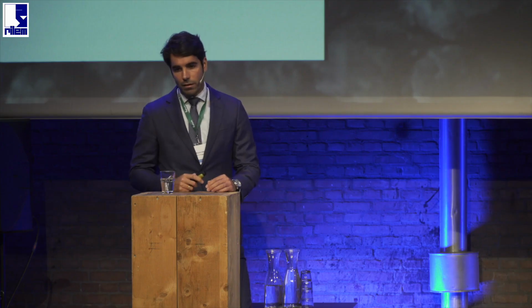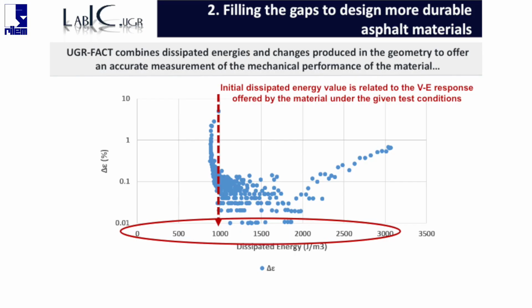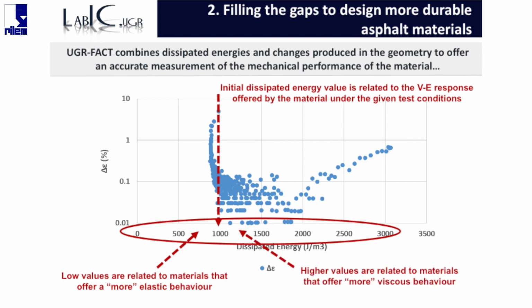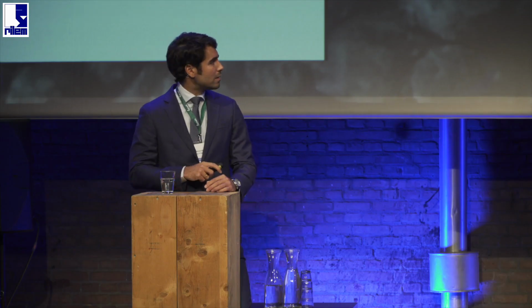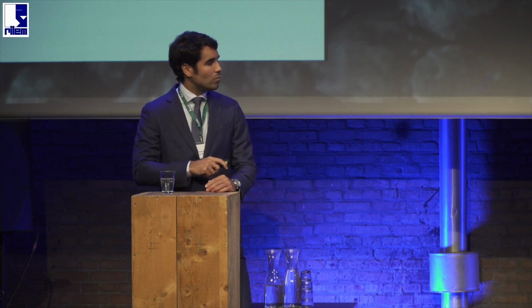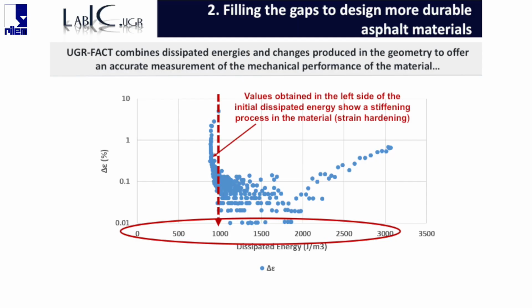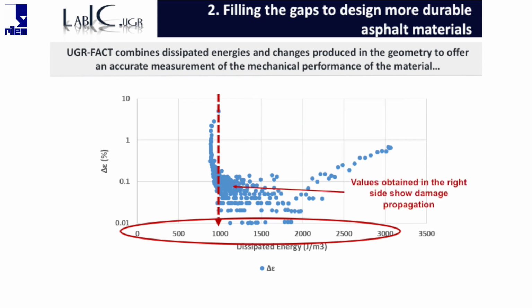Analyzing the dissipated energy, we can observe that initial dissipated energy is related to the viscoelastic response of the material under that condition that we are testing. Low values of the initial dissipated energy are related to a more elastic response, while high values are related to a more viscous behavior of this material. During the test, if the values of dissipated energy go to the left side, to the initial dissipated energy, we can observe that the material is suffering a strain hardening process due to the plastic deformation. If they go to the right, to the initial dissipated energy, that means that the material is suffering damage.